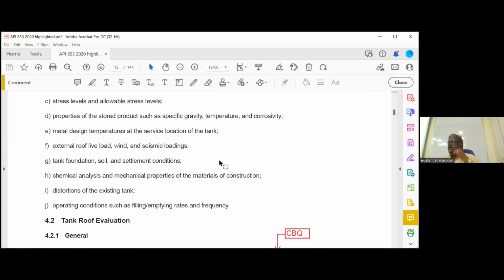Now, what are the roofs we have to evaluate? There are 3-4 points I will say. When there is a severe corroded area, we have to mark a 100 square inch area by marker. 100 square inch means 10 inch by 10 inch. How will you calculate area? Length into width, 10 by 10, 100 square inch, and you have to average the thickness in that area. You have to take thickness readings and average them. If the average thickness is less than 2.3 mm, that area is to be repaired. Point number 1. If the average is more than 2.3 mm, you can accept it. Even 2.3 is accepted. 2.3 mm means 0.09 inch.